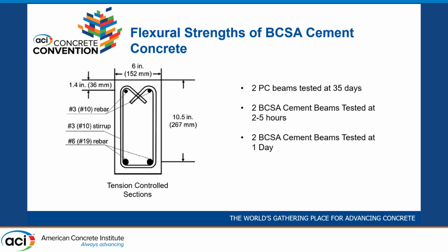Of those 6 tension controlled beams, we had 2 Portland cement control beams that we tested at 35 days of age. These were made out of the same mixture. They were from ready mixed concrete. We had 2 BCSA cement beams that we tested at 2 to 5 hours. The reason there's a range there is that this is as soon as we could get the beams out of the forms and put them in the loading frame and test them. And we also had 2 BCSA cement beams that we tested at 1 day of age.